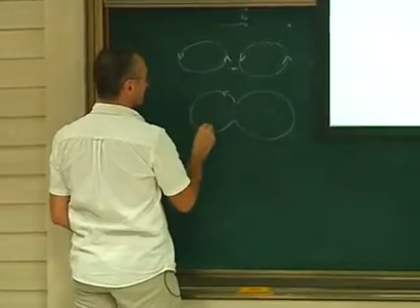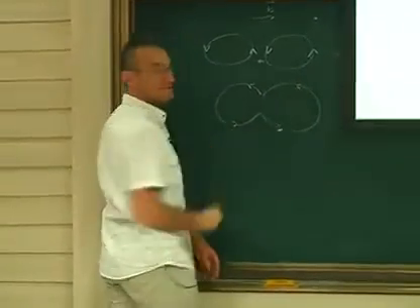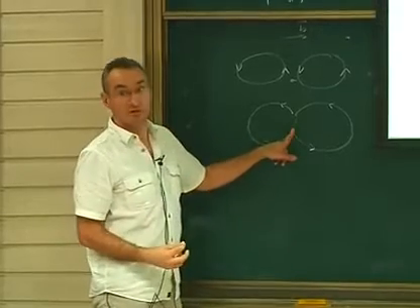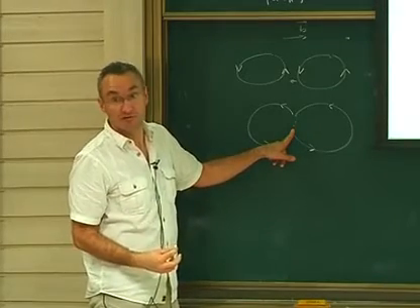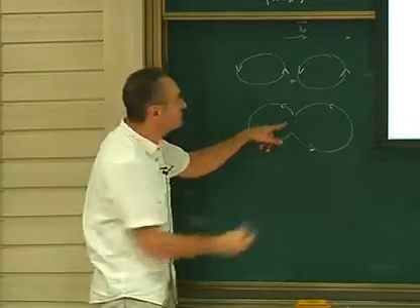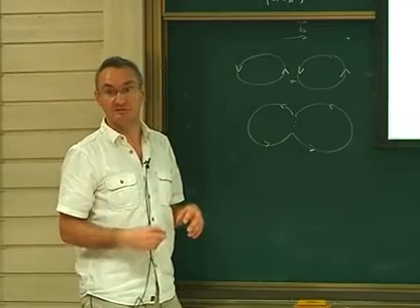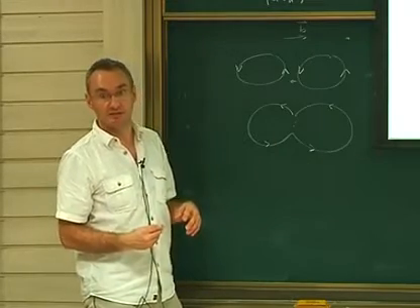Okay? This is what I told you when I say it's annihilated. Do you call this a junction or not? Anyway, this is not strong, this is even actually soft. It's a softening mechanism because it is very easy now to move. So it's not a hardening mechanism. So usually we put zero for this interaction because of that, you see?